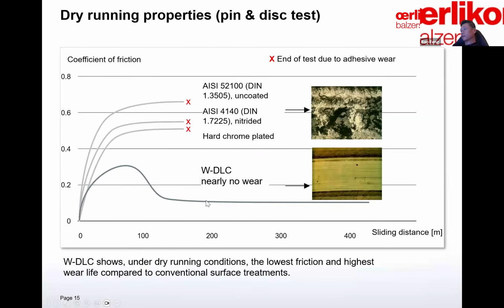And how does that low friction behavior compare to traditional surface engineering technologies, for example, hard chrome or nitriding? As you can see, hard chrome and nitriding start with a high friction coefficient under dry contact, and very soon they have a scuffing failure. But DLC goes through the initial breaking-in stage with a slightly higher friction coefficient, then the friction coefficient starts to come down to a steady state, and continues at that condition for a long time.